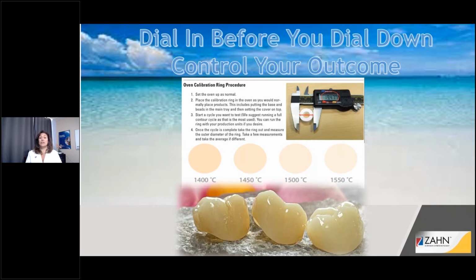Is it a big deal? It's a huge deal. If you put an A3 unit into the furnace and you're expecting that crown to come out and match fairly closely to an A3 shade tab, you can get very different results. If the furnace is sintering even 30 degrees too low or too high, you will see either more chroma than you would like, or a washed out unit not getting the desired shade, less chroma. It really does have a pretty big impact. So you want to make sure that you're calibrating, your oven is on point, and then you test your material. That'll give you good results and a good starting point to gauge what you want to do next.